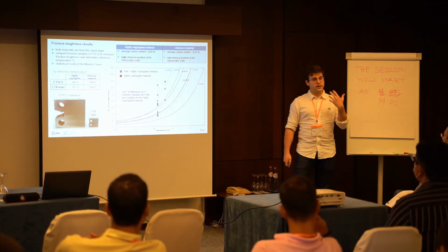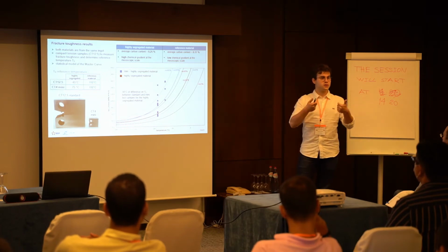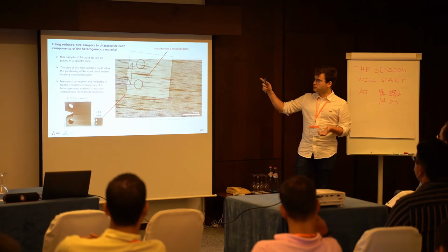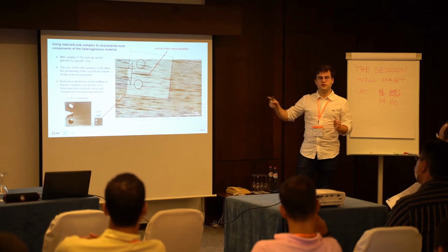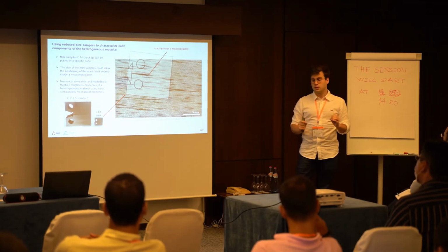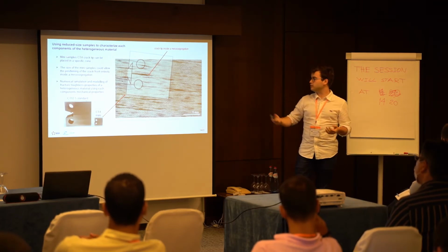But to understand this phenomenon better, we could use that increased sampling effect and the properties of mini samples, which allow the positioning of the entire crack front inside a specific zone, such as a meso-segregation or the depleted metal.